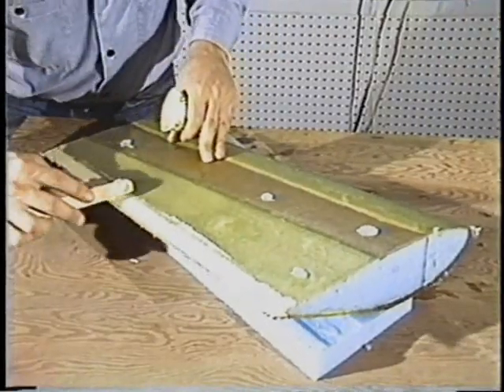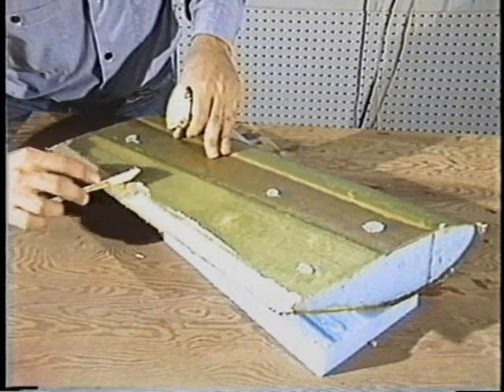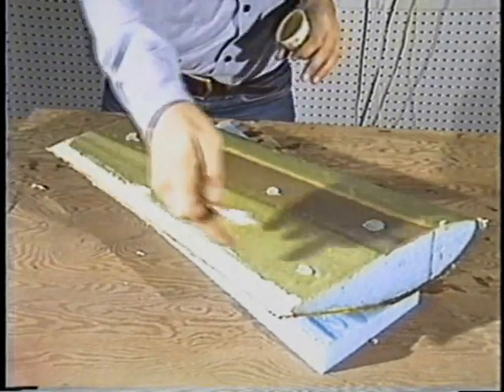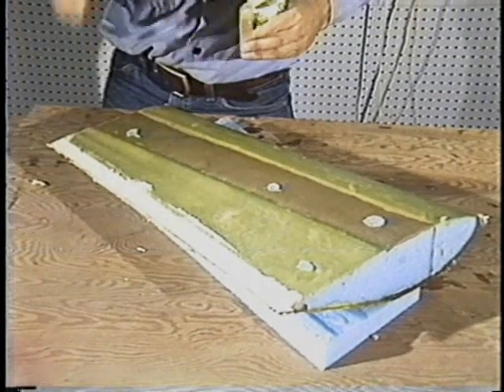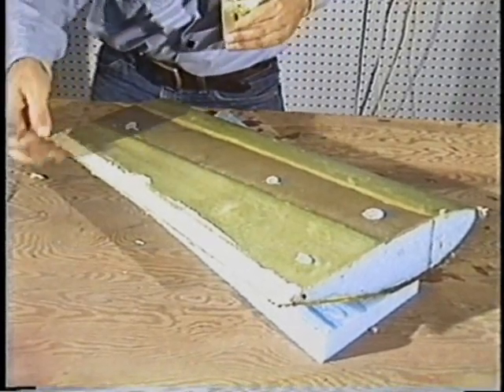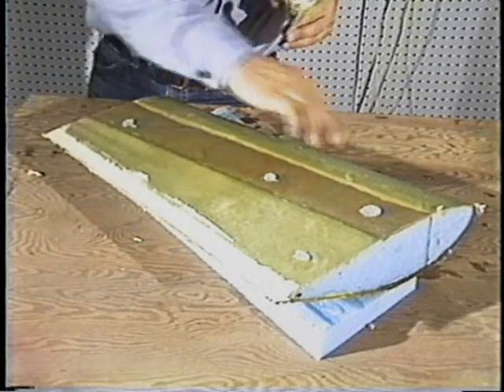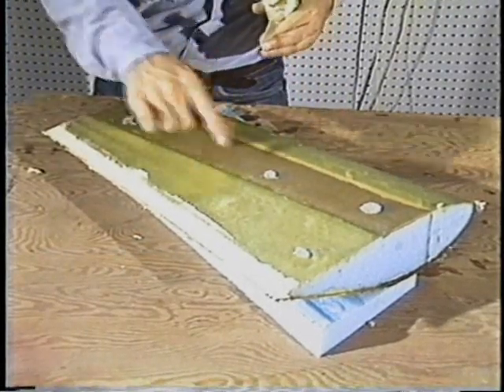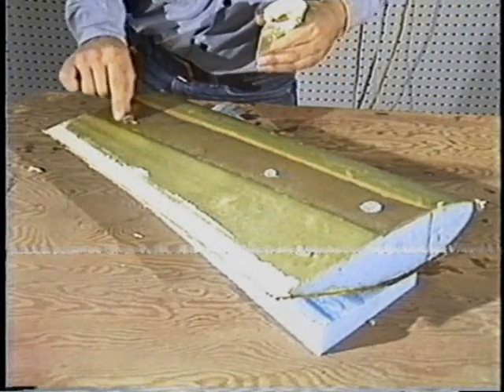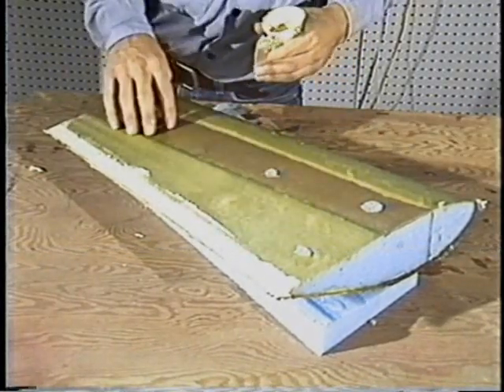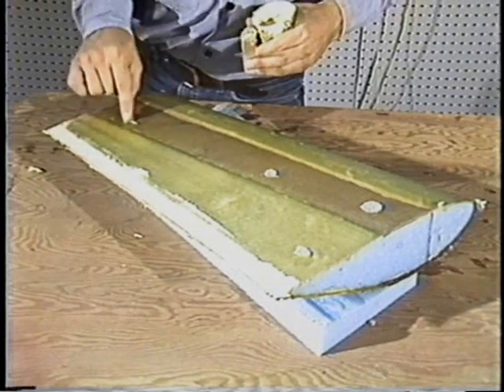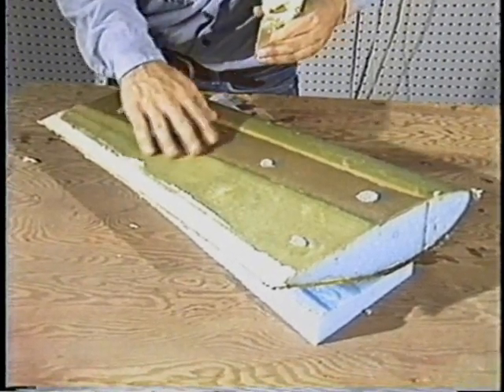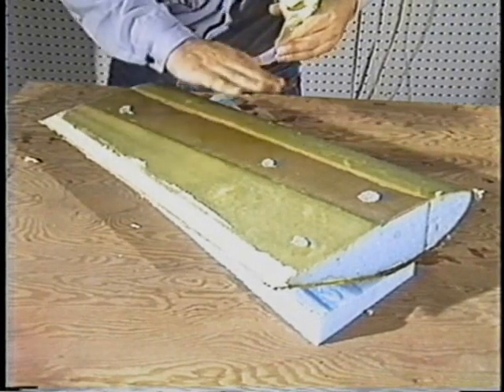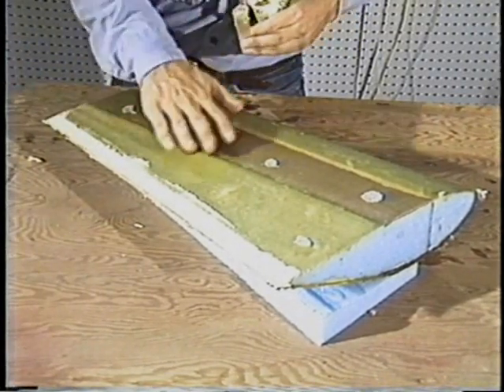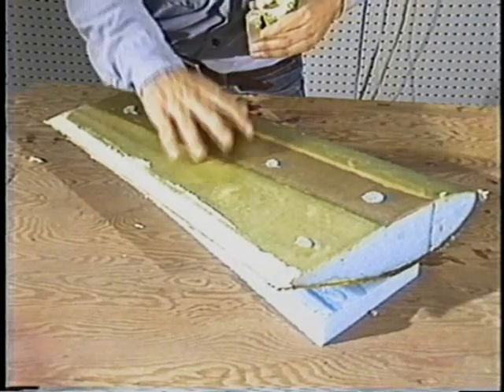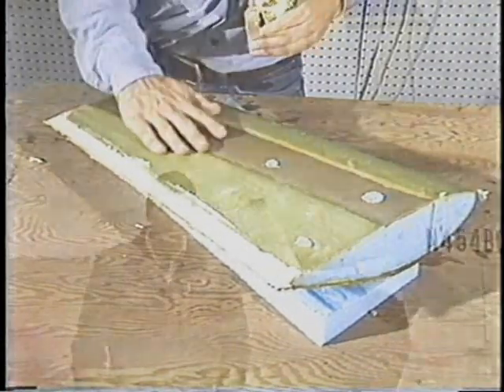Now that we've got it pretty well filled, we have a little bit of excess in a few spots. It can be easily sanded off later, and we'll trim the trailing edge when it's gotten fully cured and hard. We don't want the possibility of hitting a trailing edge and separating this. We'll also need to sand the leading edge a little bit to smooth it up, clean up some of the 5-minute epoxy that held it down for the layup on the other side, and we'll need to go through the finishing process to fill any irregularities and to give the final smooth surface that you see on a composite structure. But this structurally is essentially complete.